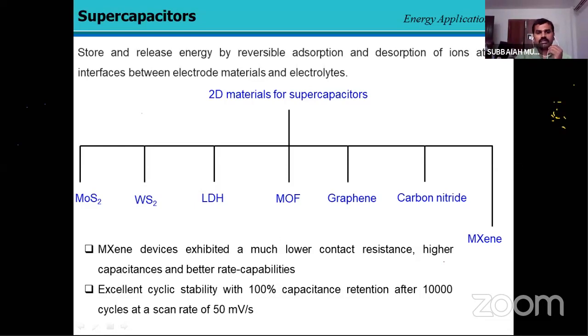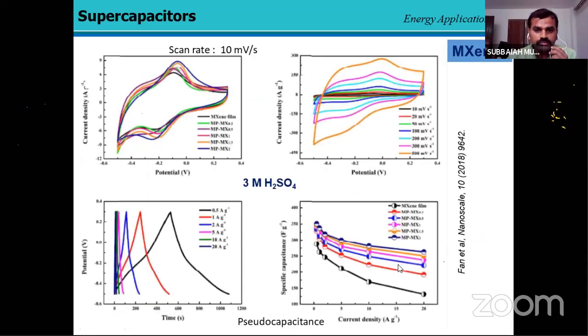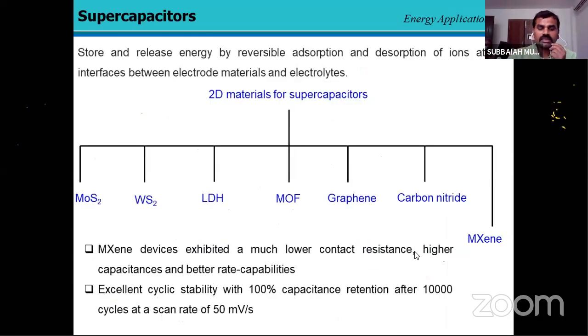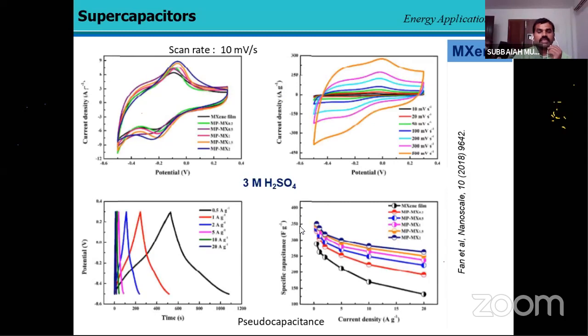Among these materials, MXene materials exhibited lower contact resistance, higher capacitance, and also showed excellent cyclic stability, with 100% capacitance retention even after 10000 cycles at the scan rate of 50 millivolt per second. Then initially, a group of people from China developed a supercapacitor application using MXene-based materials. They intentionally developed porous materials, a porous MXene phase. They found that it is the best one.